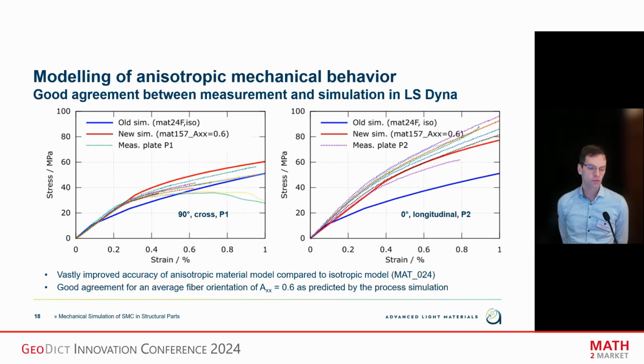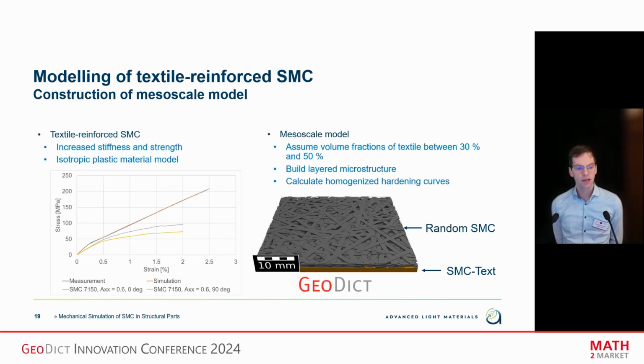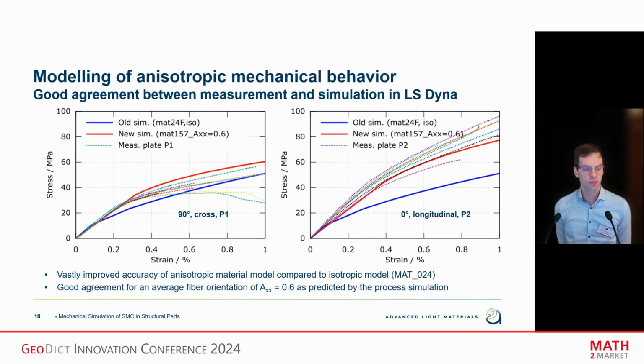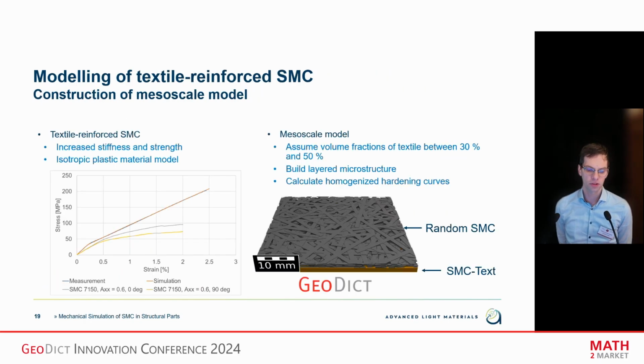Let's say there's of course room for improvement, and that's why we are also still working on the nonlinear anisotropic material function for the bundles, but the agreement is actually good. Initially in the project we started with this blue line with the isotropic card, and you see that it's a large improvement to use the anisotropic material law instead. But as I said, in this project, we don't want to stop here at tensile tests. We want to go to the component scale.